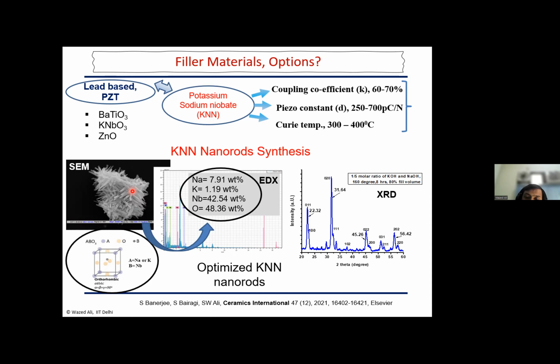So we have carried out different kinds of characterizations to prove that this structure is formed or not. And its crystal structure is very important for piezoelectricity, as I mentioned. For example, for PVDF, as I mentioned, it should not be alpha, it should be beta. And similarly for ceramic also, it should be orthorhombic, or it should be hexagonal. It should not be a cubic structure. Cubic structure is basically a symmetric structure, meaning the dipole moments are balanced. The total resultant dipole moment will be less, or maybe towards zero. So the crystal structure of the filler is also important, which we have maintained over here.